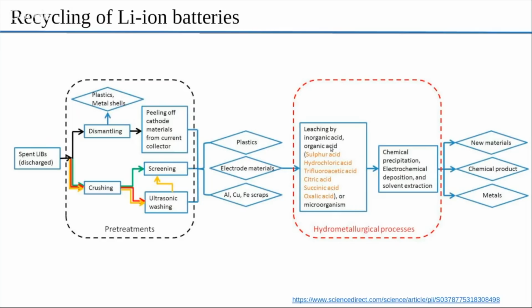And once you have done that, you have a container full of, let's say, acid that has cobalt in it. Then you subject it to chemical precipitation or electrochemical deposition, where you're able to extract some of those cathode materials in a reversible way. Once you extract the nickel or cobalt, it may not be as good as the starting material of the battery. We saw in a slide where it came out of the mine, they refined it, and it was pure. So the cobalt coming out of this process may not be as efficient or pure as the initial starting material, but that's an area of research that is happening, how to get really high quality cobalt and nickel and electrolytes or other materials from the recycling.